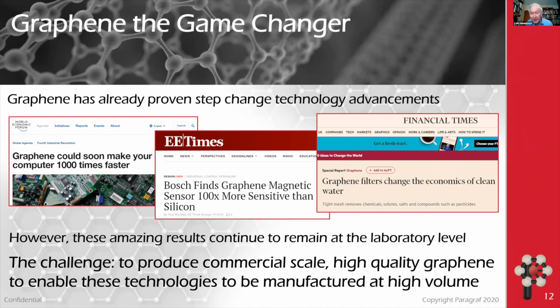And as far as I'm aware, there are not commercial graphene filters that have changed the economics of getting desalinated water. And then in the middle, Bosch finds graphene magnetic sensor 100 times more sensitive than silicon. So the whole problem is these results you can show in the laboratory by assembling things by hand using graphene flakes, but the challenge is to scale up to have larger area graphene.